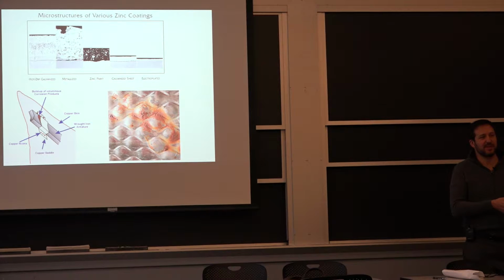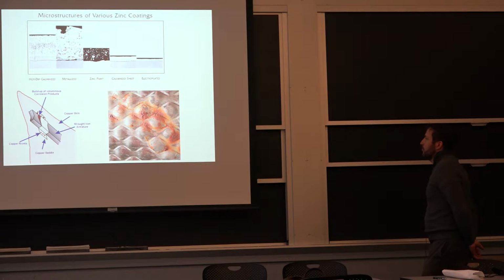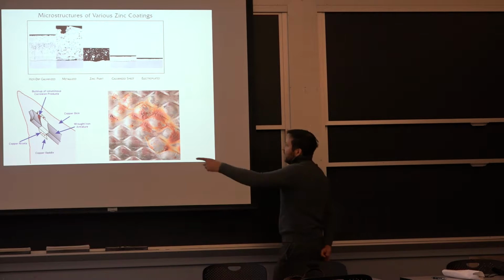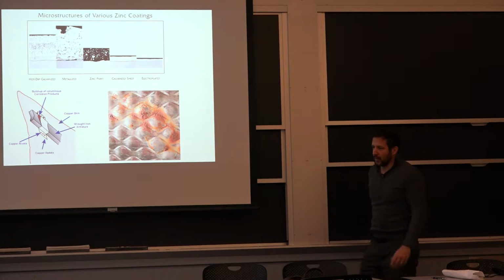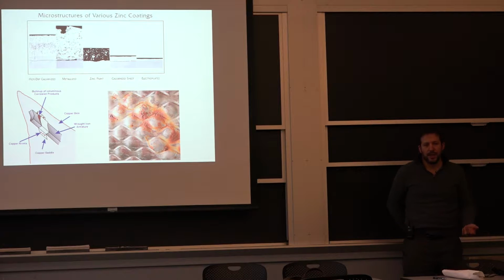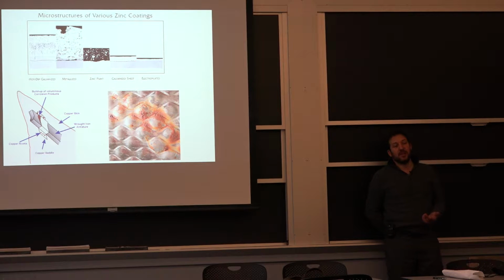So the purpose of zinc is not to have zero reaction with the environment, but to limit it. We didn't talk too much about the effect, but for a hot dip galvanized piece that's exposed to the weather, like a bridge component, you can expect about 50 years life out of the hot dip galvanized coating. And if you have the very thin layer one that's about 1/10 of the thickness, well, you're thinking about 4 or 5 years. Now, it could be as little as a year if you have salts and a lot of moisture. So that happens sometimes in tunnels.